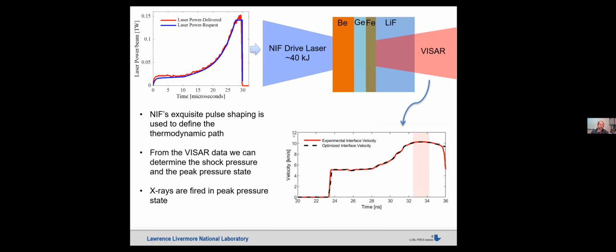Okay, so to go over that in a bit more detail, NIF is a really amazing facility because it can give you such accurate pulse shaping. We want it to be better, but it does a really great job. And so we request a pulse shape that looks a little bit like this in blue, where this is laser power in terawatts for an individual beam. And in these experiments, I apologize, this is not microseconds, this is nanoseconds. So these experiments last 30 billionths of a second, 30 nanoseconds long, where the pulse shape looks a little bit like this.